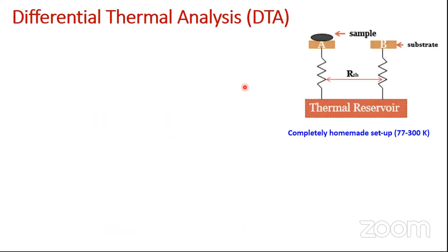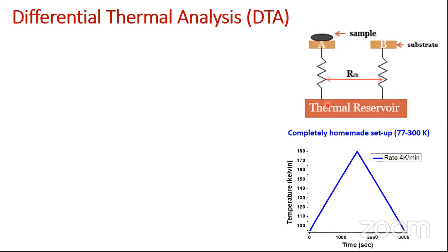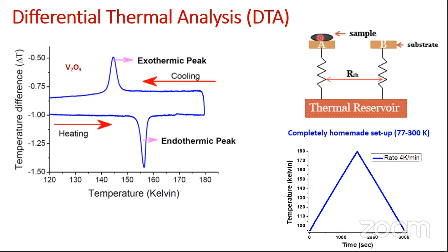We fabricated a differential thermal analysis technique, and we took two equivalent substrates which are connected to a thermal bath, and a sample is mounted on substrate A, and we are changing the thermal reservoir temperature in a ramp fashion. Now we are measuring the temperature difference of the two substrates, TA minus TB, with respect to the reference substrate B. And during this transition, the sample will absorb or release latent heat, and then one would get a peak and dip in this temperature difference, and these peak points give the transition temperature.